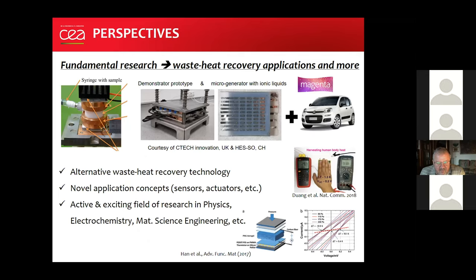So just to give you a few perspectives, with the use of ionic liquids, new redox couples, and nanomaterials, liquid thermoelectrics are now leaving the phase of fundamental research and entering into the application of waste heat recovery. Just within my lab, along with Magenta, we started out with this simplified thermoelectric cell shown on the left. And now we are building the prototype for demonstrators, micro generators for flexible and room temperature use. And soon we hope to bring out the prototype for the internal combustion engine car. And right below is another group that uses water-based thermoelectric cells, which has demonstrated that by using the temperature difference provided by a hand, so delta T of only about 1 to 2 Kelvin, they can generate a measurable quantity of electricity.